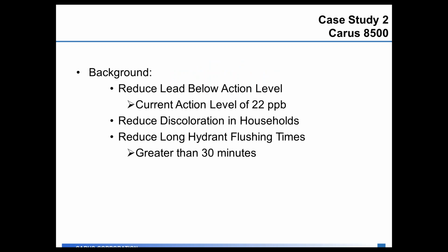Case study, this one is for Carus 8500. The background for this plant was to reduce the lead below the action level. They were currently violating the action level at 22 parts per billion, with the action level being 15. They wanted to reduce discoloration in households, as they were having staining on fixtures and laundry in homes, and they wanted to reduce the long hydrant flushing times. When they were going out to flush hydrants in the distribution system, it would take them greater than 30 minutes of flushing water before the water in the hydrant would clear up.